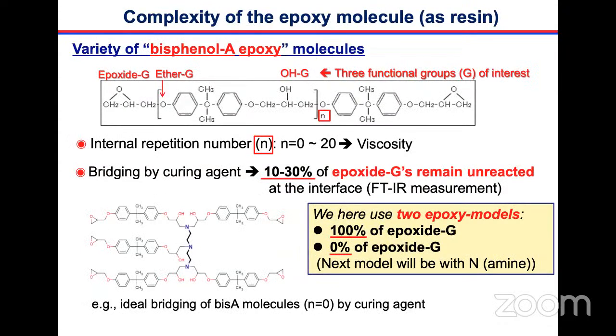The epoxy molecule we use is shown here. This is called a bisphenol A epoxy molecule. You have the epoxy group here, the ether group here, and the hydroxyl group here, three functional groups of interest for us. And then we have the repetition number n. So n ranges from 0 to 20 according to the experiment. Of course, a large n means large viscosity.